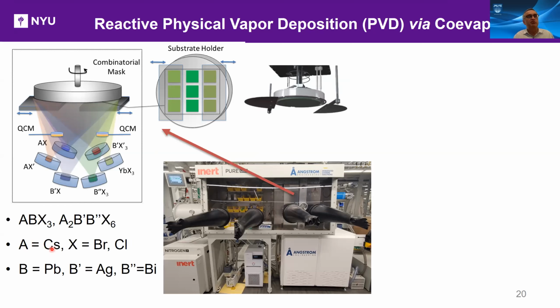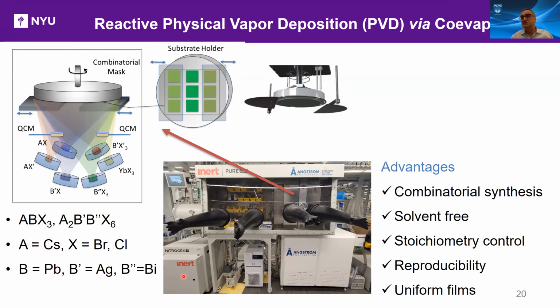The sources that I'm going to talk about, we have many, we have all the metal chlorides and bromides in this chamber. I'm going to talk about cesium chlorides and bromides, lead chlorides and bromides. Actually, I'm not going to talk about that much, but silver and bismuth compounds in a minute. There are advantages. Combinatorial synthesis is solvent-free. Stoichiometric control, we have very good stoichiometric control with most of our precursors, except those that are highly volatile.